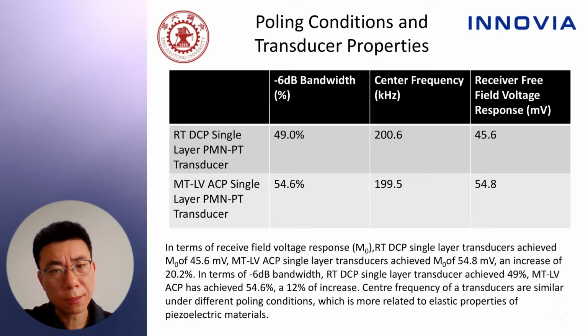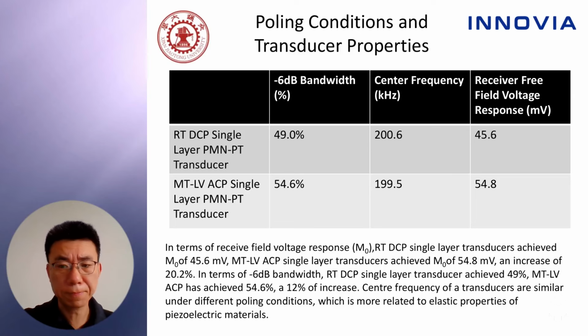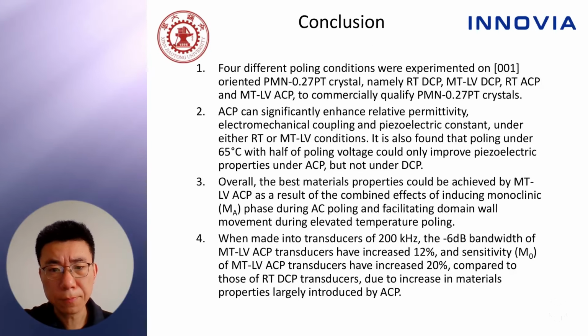This is because the center frequency of the transducer is usually determined by elastic properties of the piezoelectric materials and transducer configurations. Here are the conclusions. 4 different poling conditions are experimented on 001-oriented crystals, and AC poling can significantly enhance the key properties related to transducer performances. It is also found that poling under 65 degrees Celsius with half the poling voltage of conventional poling can improve piezoelectric properties under ACP, but not so much under DCP. Overall, the best condition on the materials achieved was MT-LV-ACP, resulting from the combined effect of inducing monoclinic phase and facilitating domain wall movement.